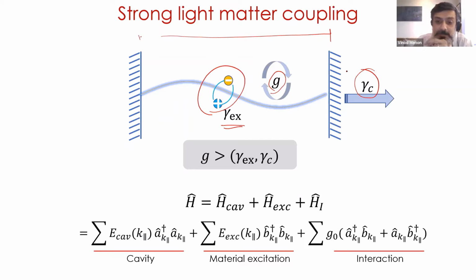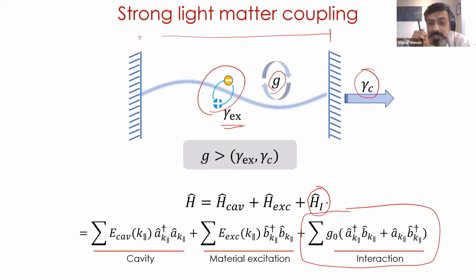In this case, the Hamiltonian can be given as the sum of the cavity plus exciton plus the interaction term. This is the term that we are most interested in, and that term is essentially this term here, which tells you the increase of a photon number and a decrease of an exciton number, and then the other way around. So this is your interaction term, and when this term becomes important, that's when you get into the strong coupling regime. To make this important, this is the condition that needs to be satisfied.